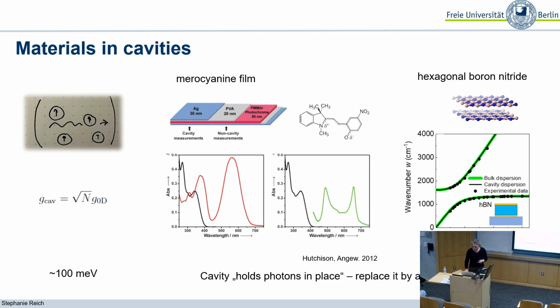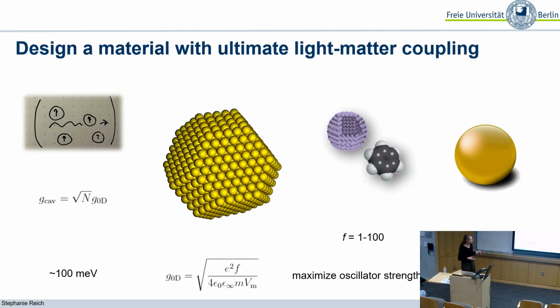So our idea was to look for a crystal and to design a crystal in such a way that we would ultimately get strong light-matter interaction. So here we have a crystal, and we considered this expression that we had for the light-matter interaction strengths. We didn't really know what we were doing with the mode volume here, but we had the feeling that we were increasing it very much. So the idea was, in order to get strong light-matter interaction, we should maximize the oscillator strengths of the individual building blocks. We later found out that this way of thinking was actually not fully correct, because the mode volume is not that important, but that was our starting point for the idea.